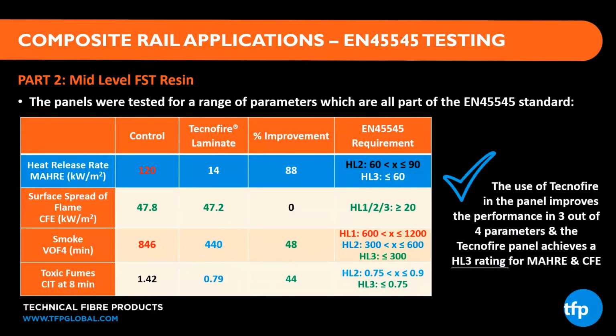The smoke is interesting. The smoke is quite a poor level. It's not as bad as the styrenated orthophthalic resin, but it's 846. So it's in HL1, the lowest level of performance. And we've improved that by nearly 50% by incorporating that layer of Tecnofire, down to 440. So we've got a really good mid-level HL2 performance just by dropping in that functionalized surface veil.